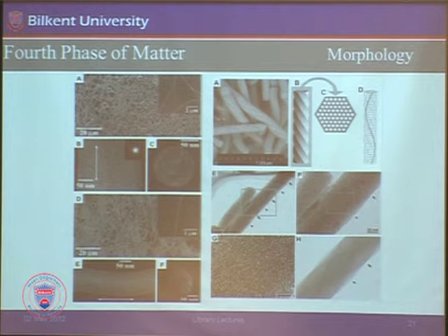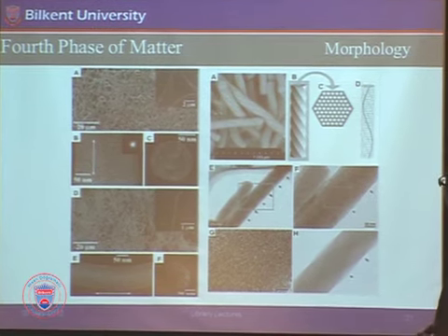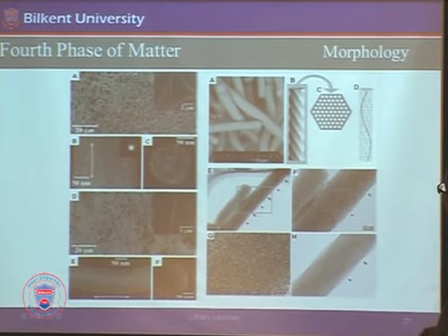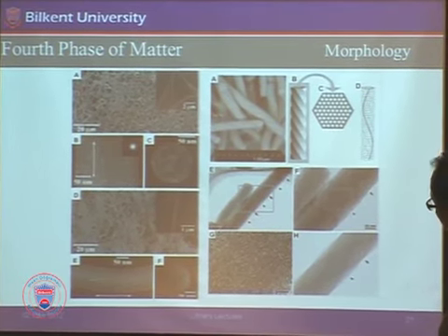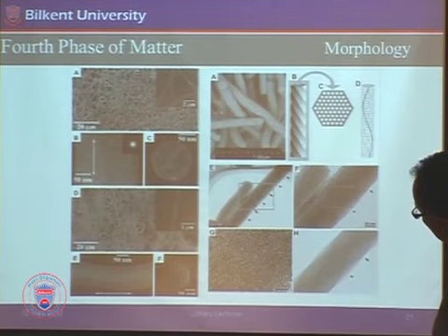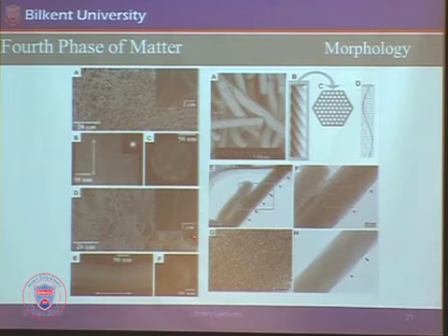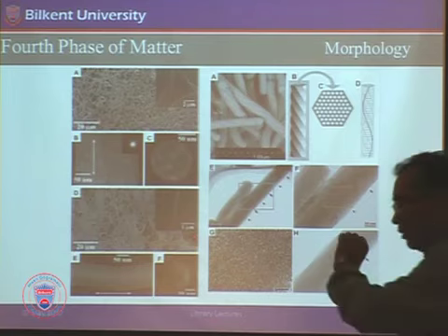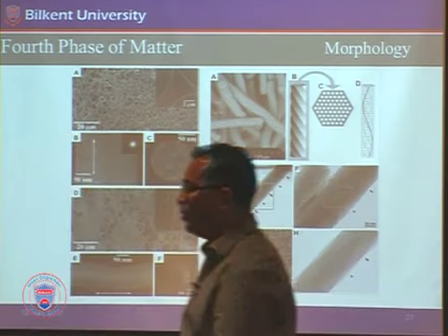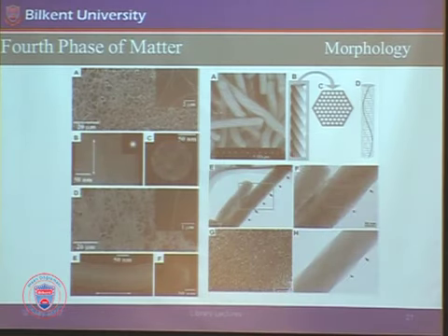And by playing with this surfactant chemistry, you can play with the outcoming material. These are like fibers. And in these fibers, this is a single fiber, you have channels, those holes, going through from one end of the fiber all the way to the other end. And those holes, like tunnels, can be as small as a few nanometers, okay? Extremely tiny. There is no technology you can drill these types of holes in these materials. Even the most advanced technology cannot do this.